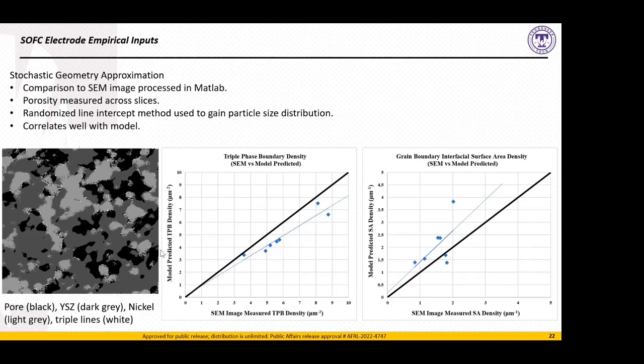And we find, here's a sample of an anode. In white, you have the triple lines between the grains. This is where electrochemical reactions can take place. And using our model, it correlates well with the values computed directly from SEM. So here we have the triple phase boundary density, and we have the grain boundary interfacial surface area density as well.